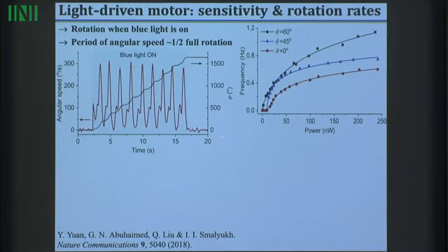And so what breaks the symmetry of which way it spins? So it can be spontaneous when your polarization is parallel to the far-field director. There is equal probability of one or the other. But if you rotate that polarization a little bit in one direction, then that coincides with the direction in which it will spin. So then there is coupling through optics. Is the local structure chiral?